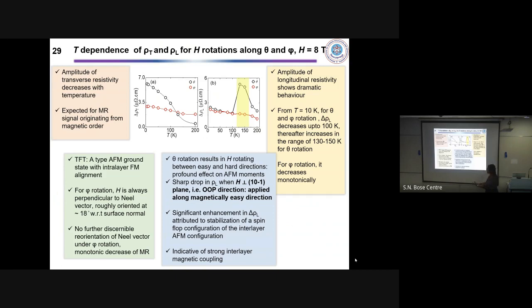So what is happening? No further reorientation of the Néel vector under phi rotation is occurring, which results in a monotonic decrease of the magnetoresistance. However, if we look into this picture, for theta rotation, that results in the magnetic field rotating between the magnetically easy and the hard directions, and that brings in a profound effect on the antiferromagnetic moments.